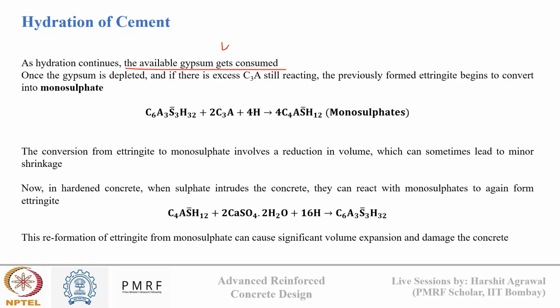Okay, because we are adding it in very small proportion, only 4% is present in cement composition. So once this gypsum is depleted, and then still if there is excess C3A which is present in my cement, what will happen? This ettringite will begin to convert into monosulfate.